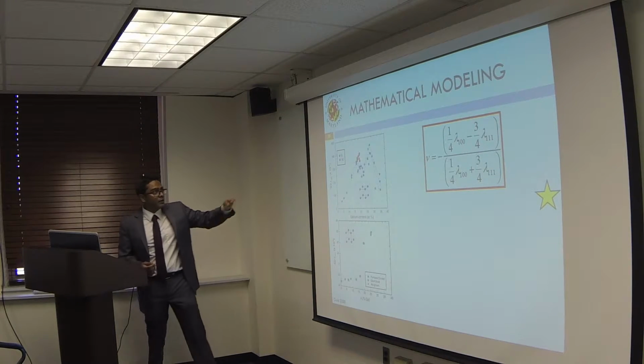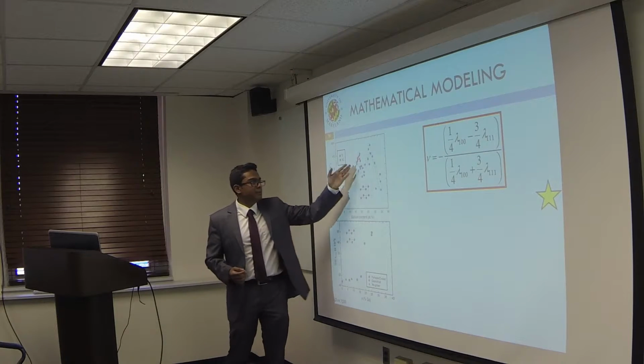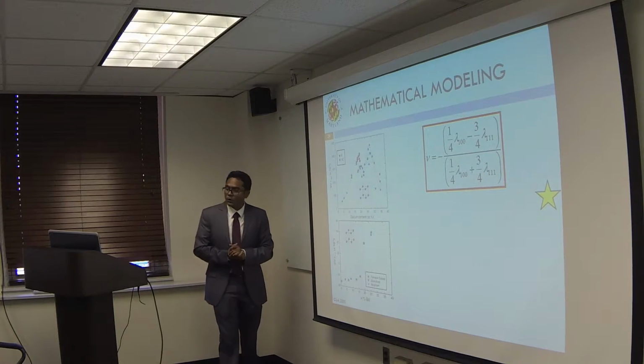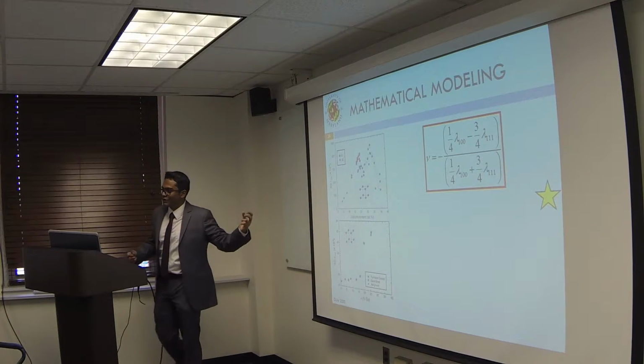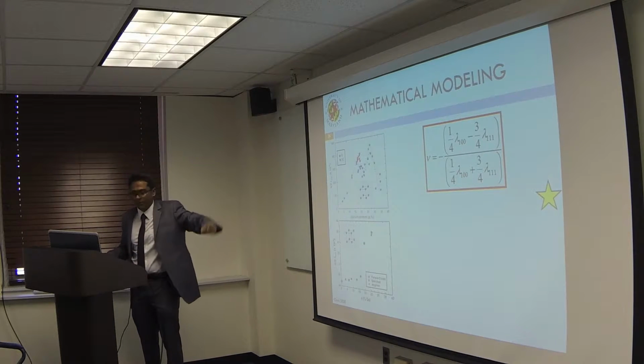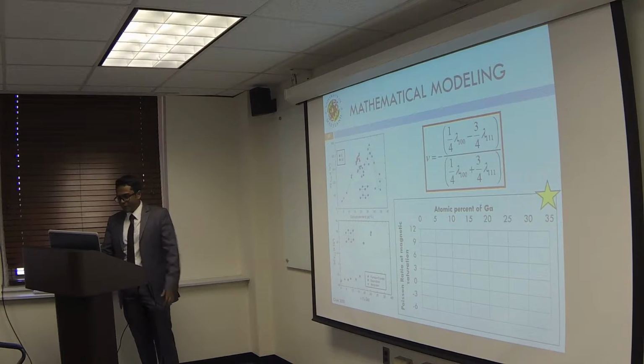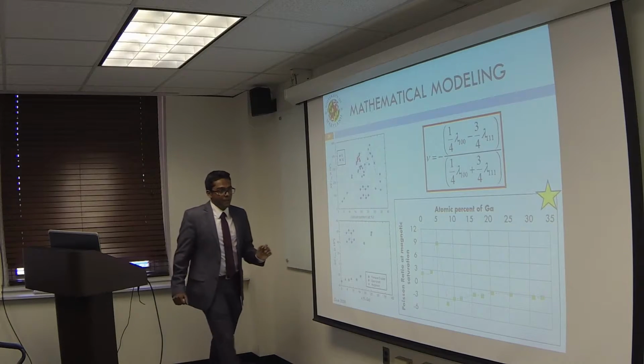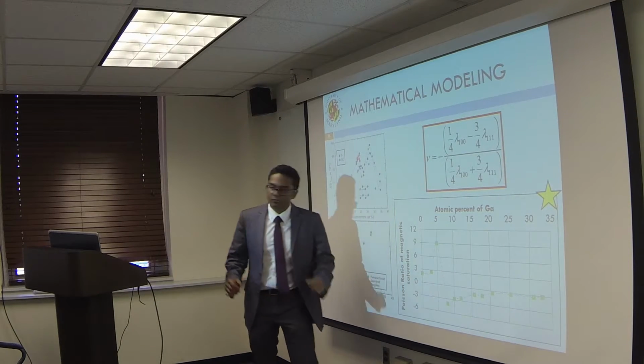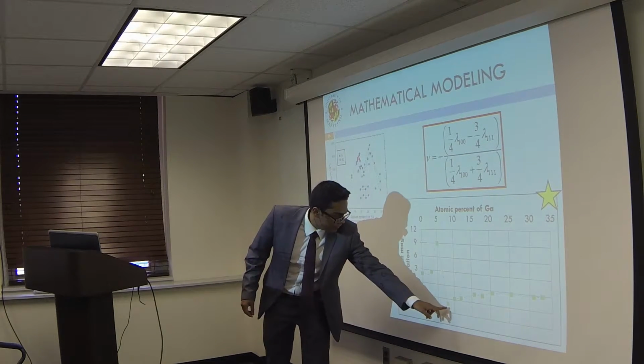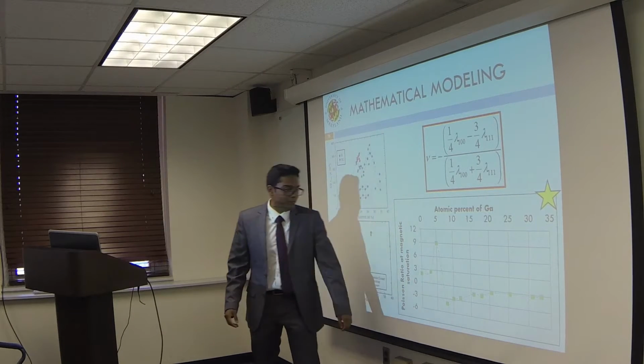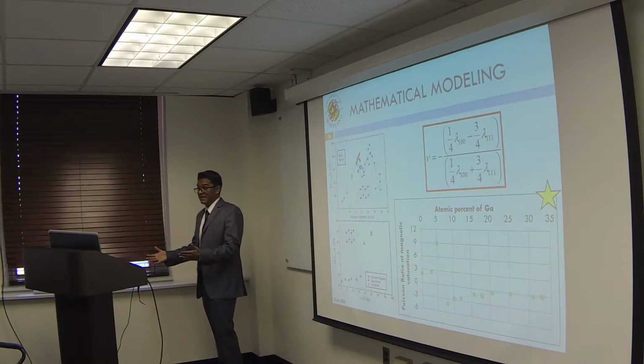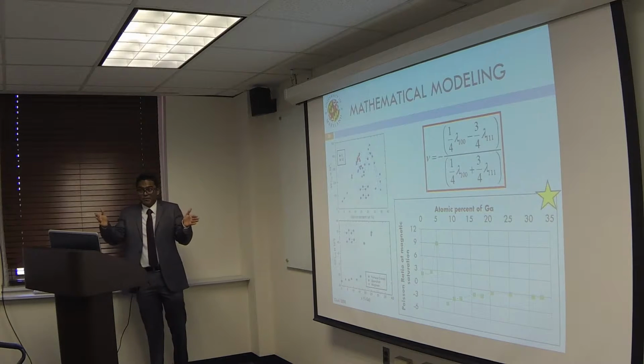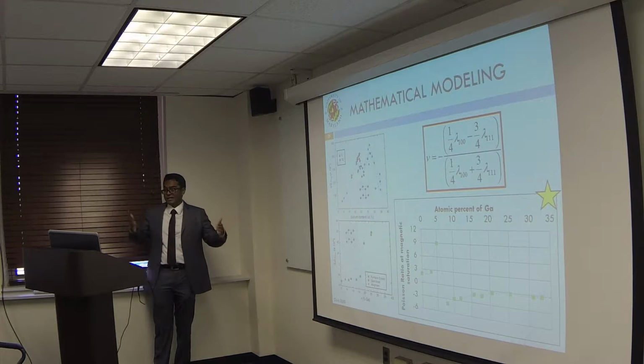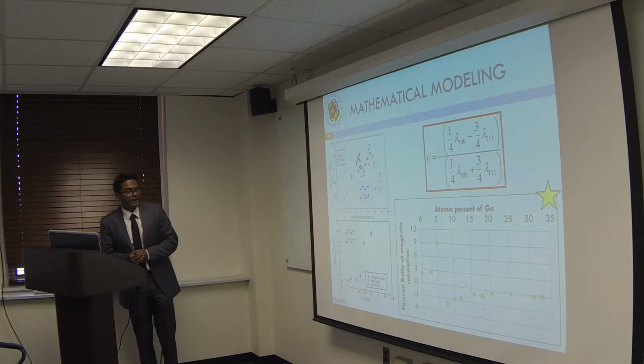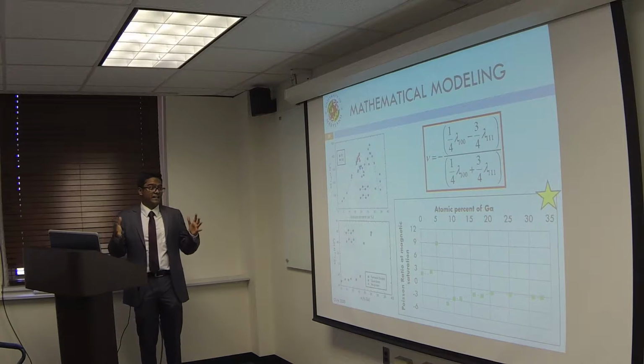Now, if I go back to literature, I already know the published values of lambda 100 and lambda 111. So I decided to pick values of lambda 100 and lambda 111 and plug them in there. And what I found was very, very exciting, because past the region where you have random phases, you're expected to find Poisson's ratio values as low as -3, which means you're getting 3 times as much strain in the transverse direction as you would get along the longitudinal direction. So this was very exciting.